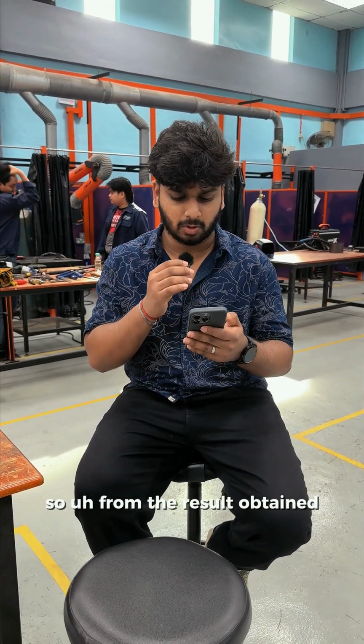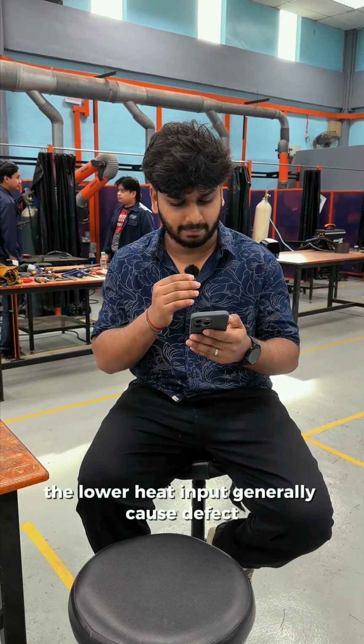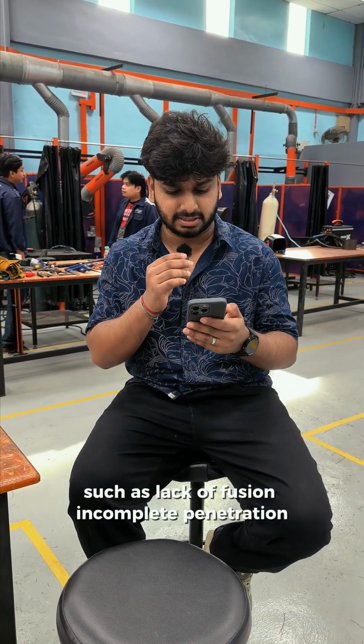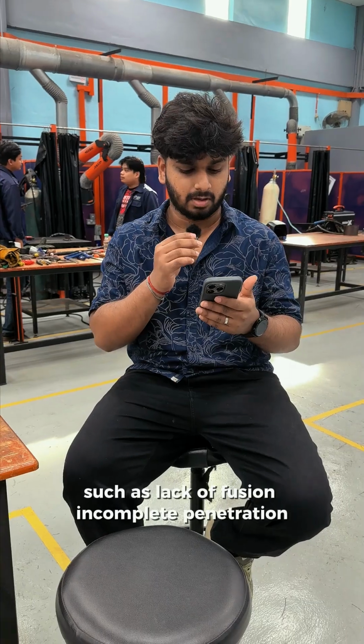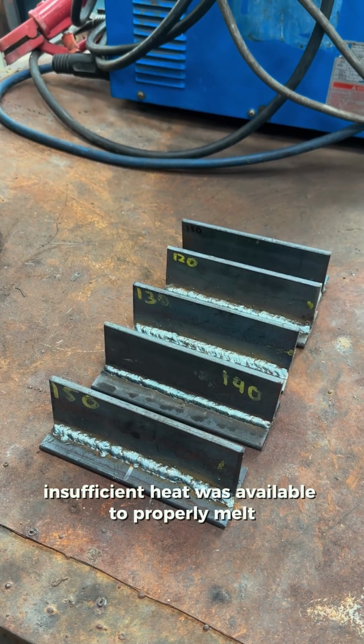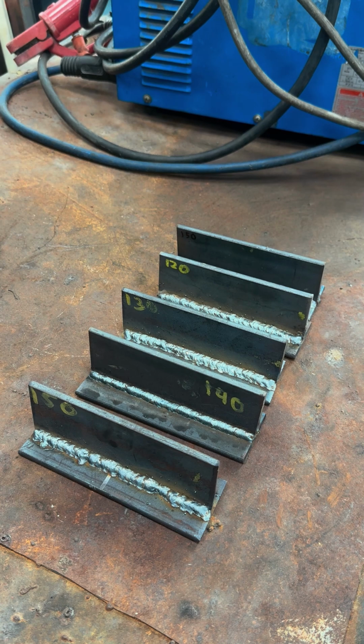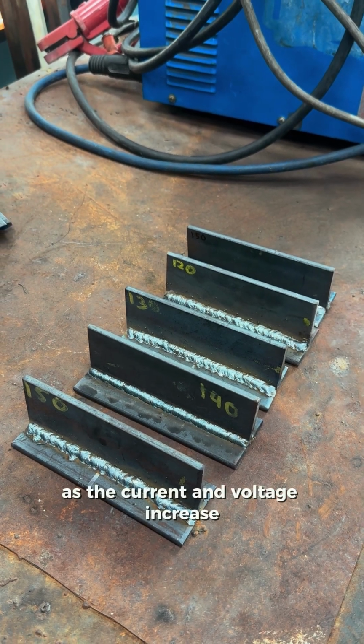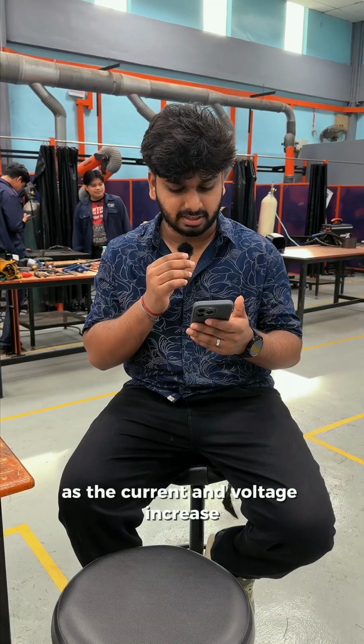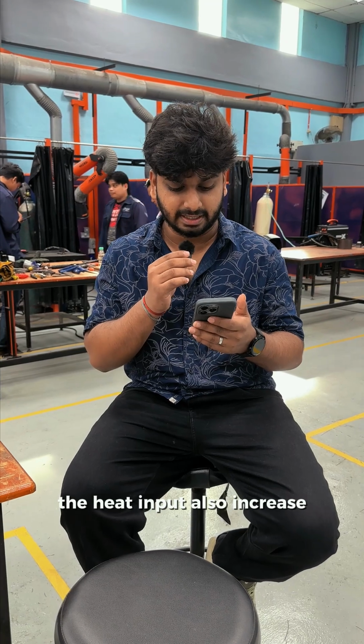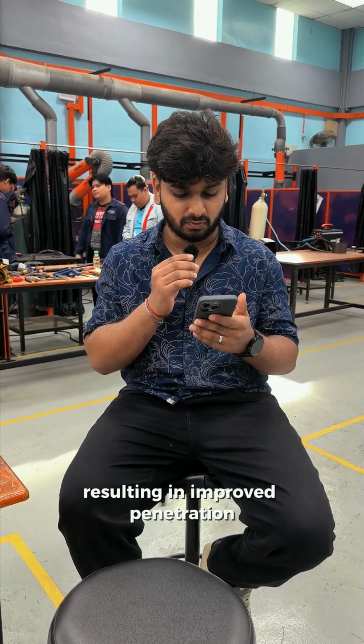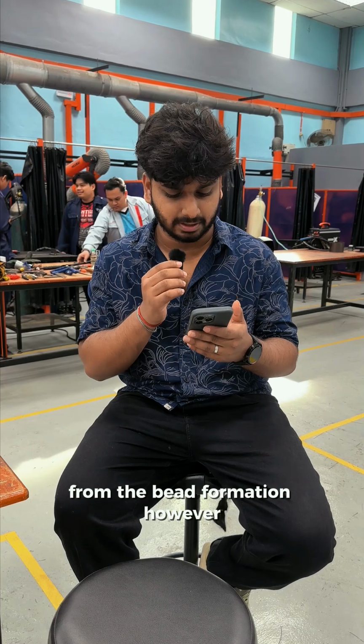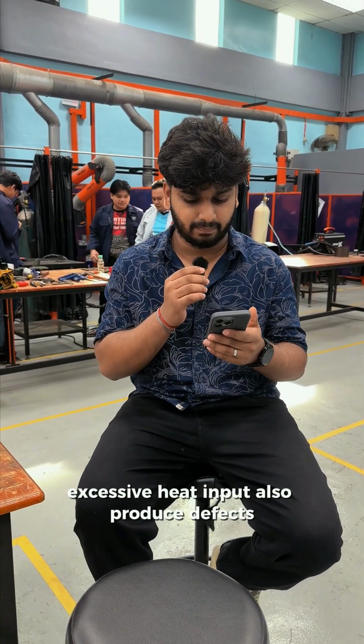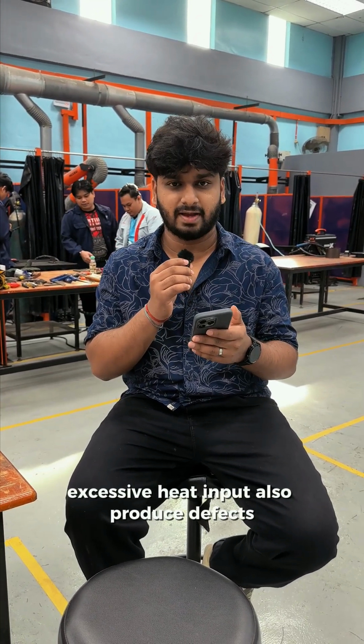So, from the results obtained, we observed that lower heat input generally causes defects such as lack of fusion and incomplete penetration, because insufficient heat was available to properly melt the base metal. As the current and voltage increased, the heat input also increased, resulting in improved penetration and bead formation. However, excessive heat input also produces defects.